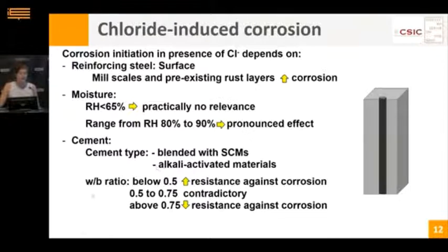Regarding the water binder ratio, it has very different behavior according to its value. For values below 0.5, it increases the resistance against corrosion. Between 0.5 and 0.75 it is contradictory, and values above 0.75 decrease the resistance against corrosion.